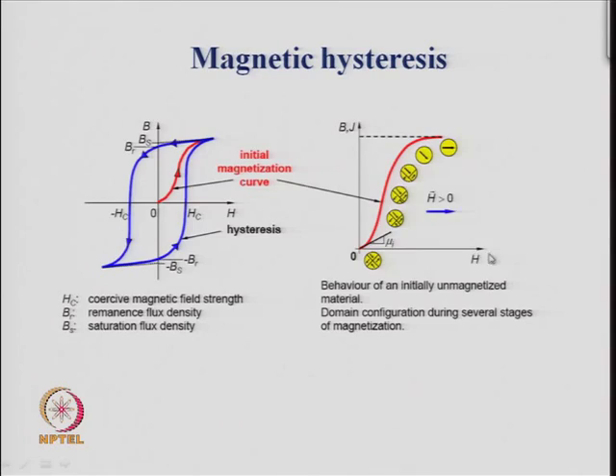If you increase the field further, there will be no further change because this moment cannot grow any further. There are no new domains to be added to it, and so the net magnetization becomes constant, and this is the explanation of this red curve here. So, you can see different stages of how the magnetic dipole vectors and the domains are changing as a function of the applied magnetic field.